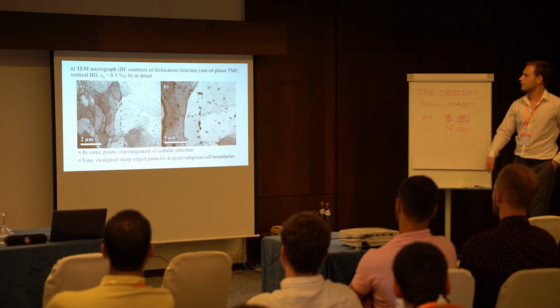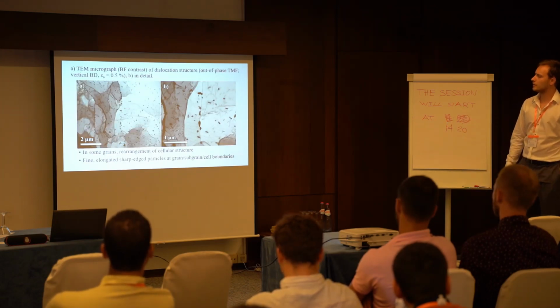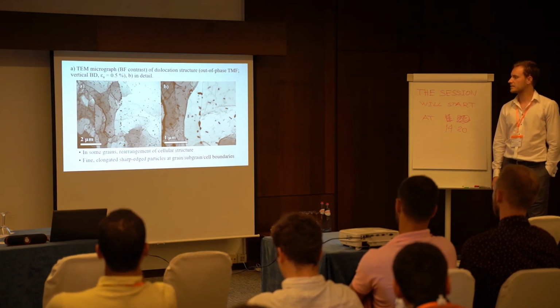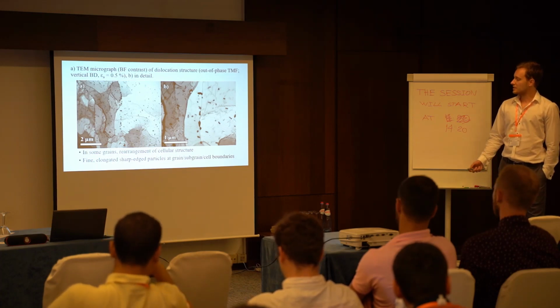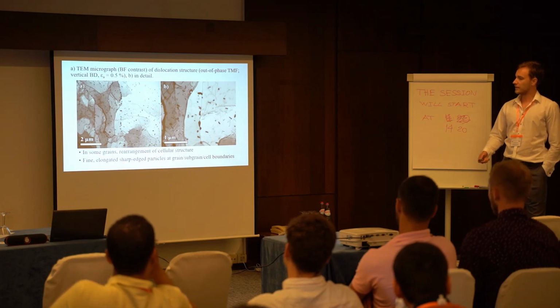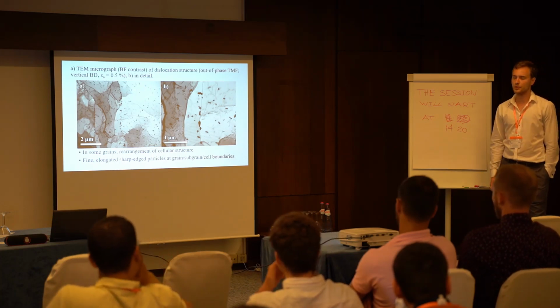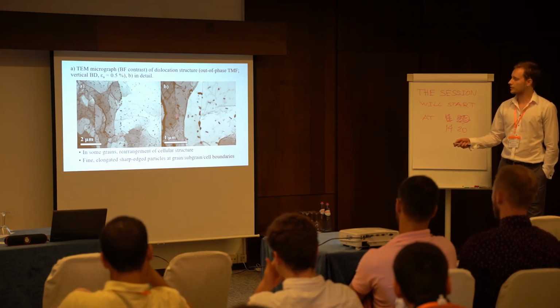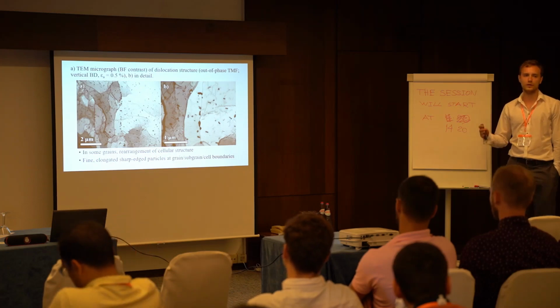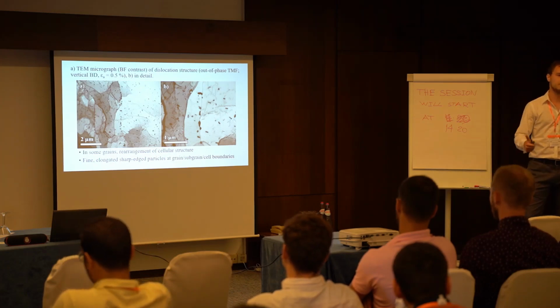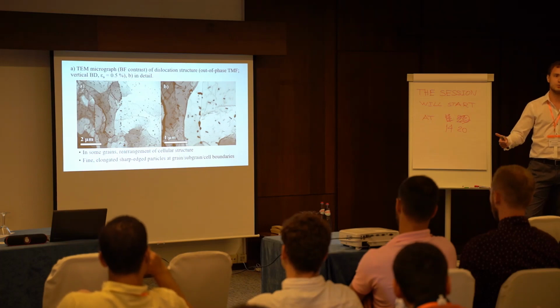Here is how the structure looks after out-of-phase tests. Obviously, thanks to the longer exposure at high temperature, more of those particles nucleated. And this time not only at the grain boundaries, but also at subgrain boundaries, dislocation cell walls, and also at oxide precursors.